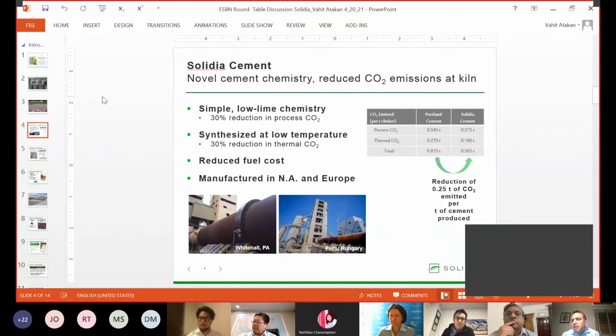When you sum them up, like I said, it is 0.8 tons per ton of clinker for OPC, and for Solidia clinker we are talking about 0.565 tons. As of today, we made 4 productions, 3 of them in Whitehall, Pennsylvania, and 1 in Pest, Hungary. And we confirmed our CO2 reductions during these industrial productions. The cement making process is right now quite simple, straightforward, and can be applicable to most of the cement plants in the world. Vahit, as you are changing slides, could you please put yourself in slideshow mode? Then we will see your slide coming out bigger.